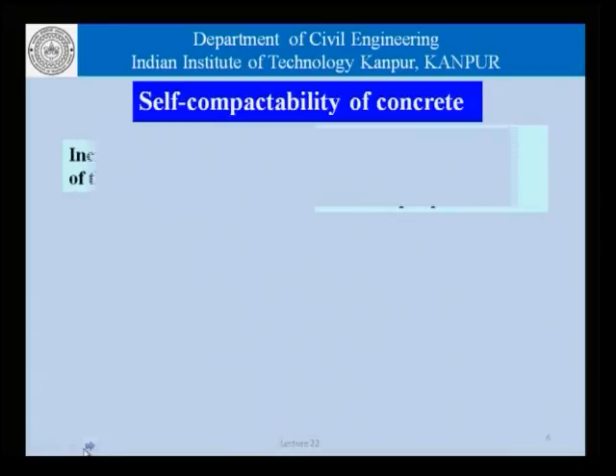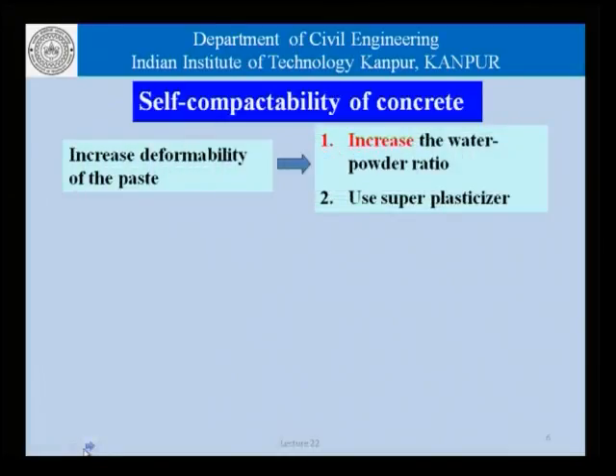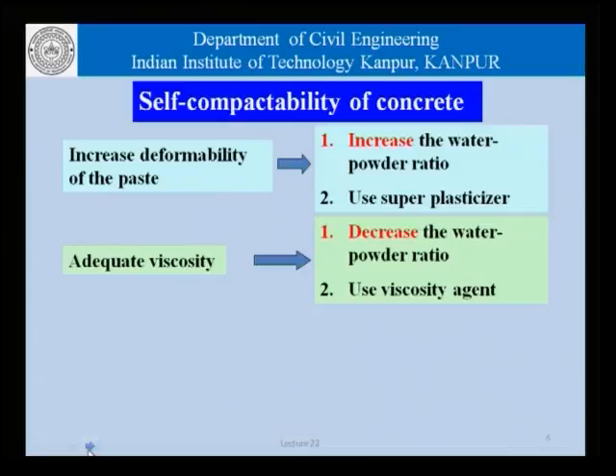We now talk about self compactability of concrete, where we said that on the one hand we need increased deformability of the paste, which calls for an increase in the water to powder ratio and the use of superplasticizers, and on the other hand we require adequate viscosity, and for that we need to reduce the water powder ratio and we use viscosity agents. So, these two are the chemical admixture route, or this is the physical route where we are trying to change the water powder concentration in the system.